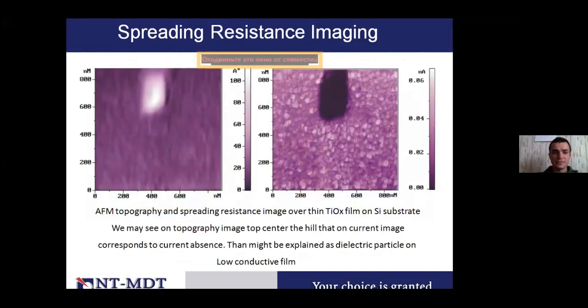Here are other examples, which you can see here. The sample here is a titanium oxide film on a silicon substrate. You can see on the left, again, the topography with a scan size of about 900 nanometers. On the top area, you can see some particles, which most likely have dielectric properties. So it's not conductive. Therefore, on the right image for the same area, you can see that in the area where we have the particles, there is no conductivity at all. We apply the voltage, we try to increase it, but still no conductivity, which helps us to understand that these particles are not conductive, so it's not titanium oxide, and maybe it can go to some further analysis of the sample.